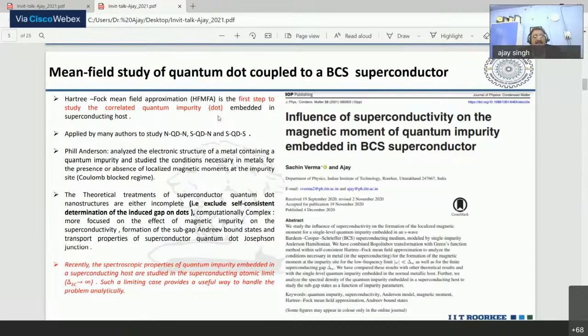The first step we have done is a mean field study. And this is quite different from the Anderson idea, where they have a metal and impurity hybridized together, and there are many possibilities in terms of the localized magnetic moment. So here the physics is a singlet-doublet transition. But if you switch on a superconducting state, there is one more component. There are resonant bound states due to Andreev reflections, and at the same time there is a possibility of singlet and doublet phases, and this doublet phase becomes robust in a certain regime. So these spectroscopic scale studies compel us to take the limit where the superconducting gap can be taken quite large, comparable to other parameters.